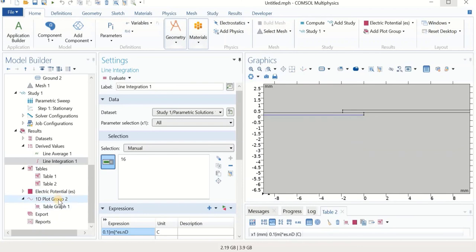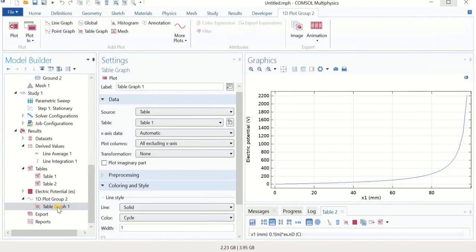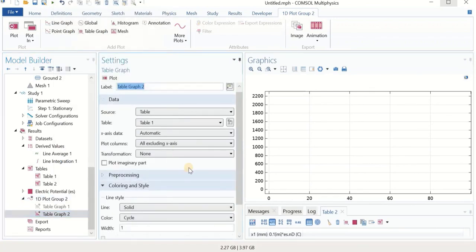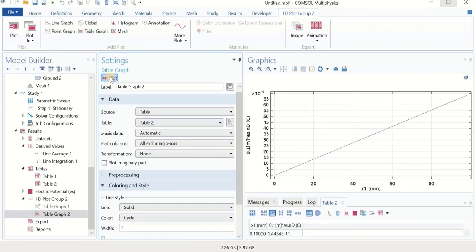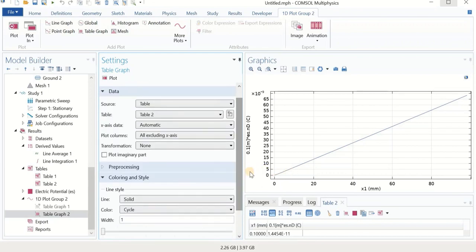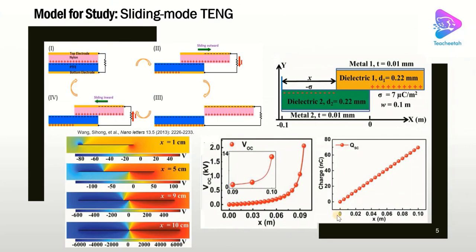The results are calculated and we have X and charge in table 2. We create a new 1D plot group with a table graph using table 2 and click plot. We get a curve — changing the units to nanocoulombs shows the charge changing from 0 to around 70 nanocoulombs as X changes from 0 to 100 mm. Comparing to the reference, we get the same values: as X changes from 0 to 10 centimeters, the transfer charge changes from 0 to about 70 nanocoulombs.